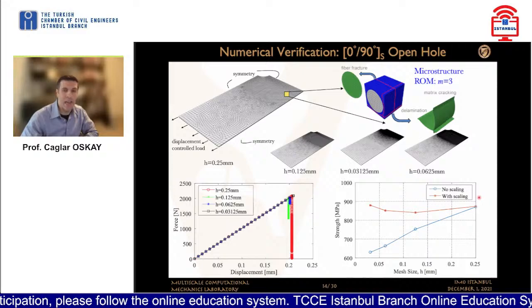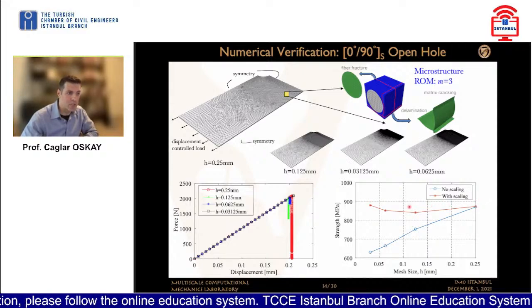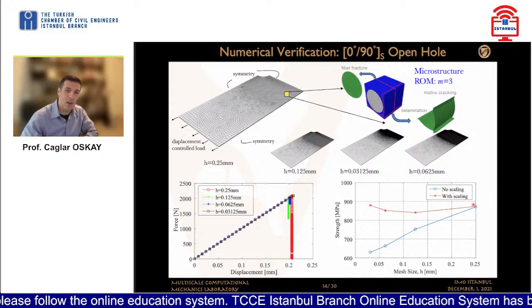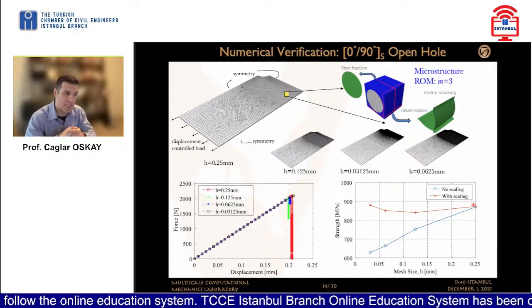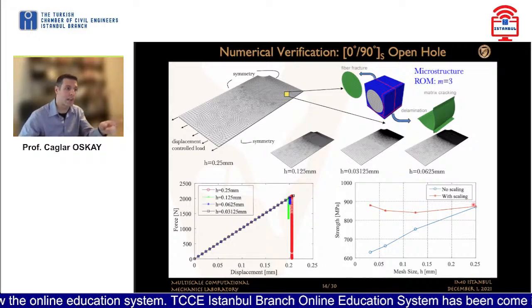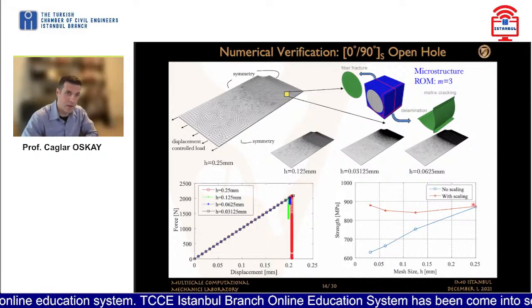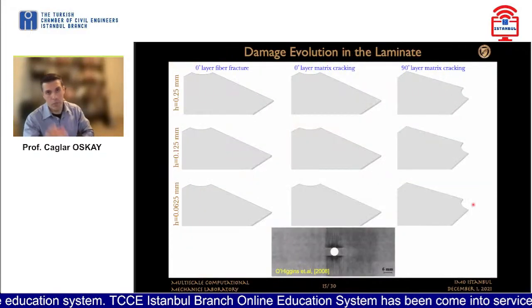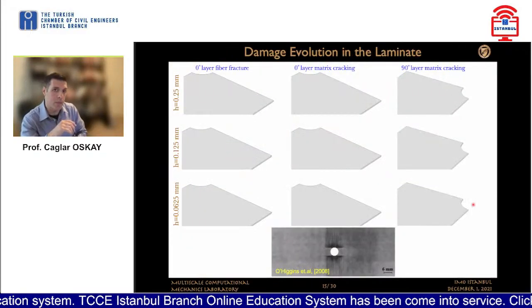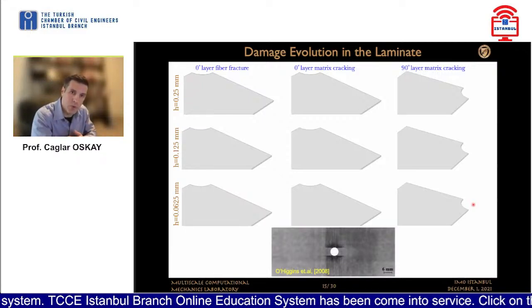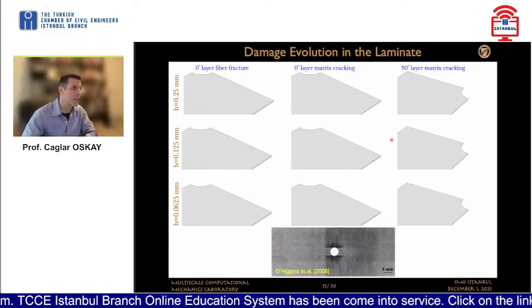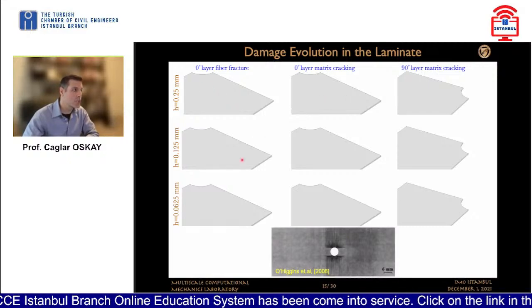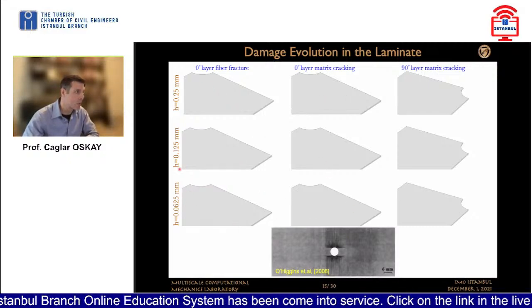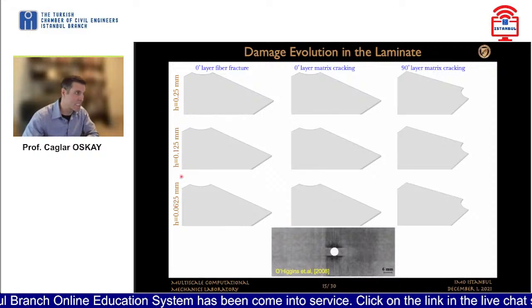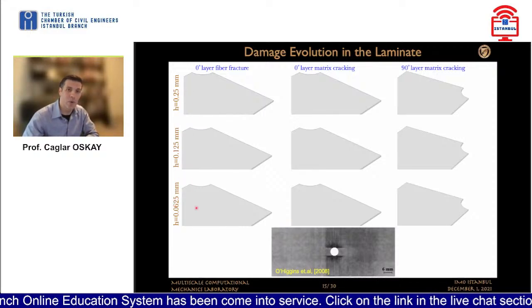Once you apply our scaling, the proposed regularization strategy, you basically obtain more or less constant strength predictions regardless of the mesh density. Even more important, let's dive a little bit more into how the damage is progressing under these. What we're showing here are three different rows with three different simulations with three different mesh densities, from the coarsest to finest, from top to bottom.